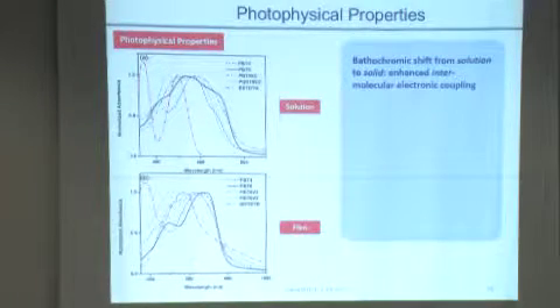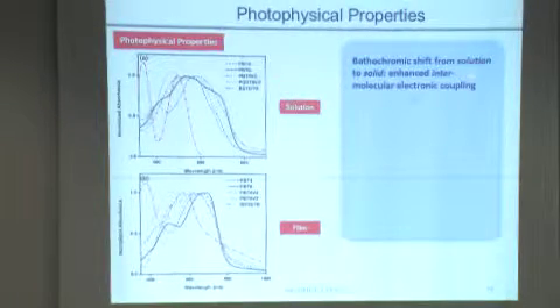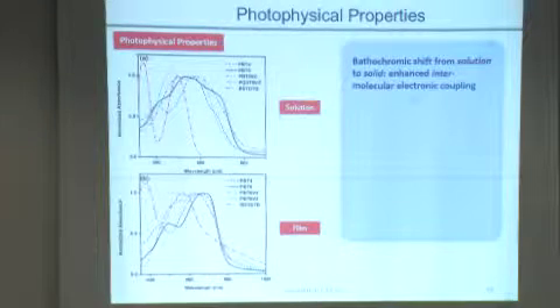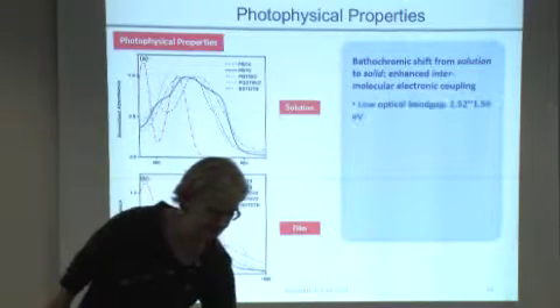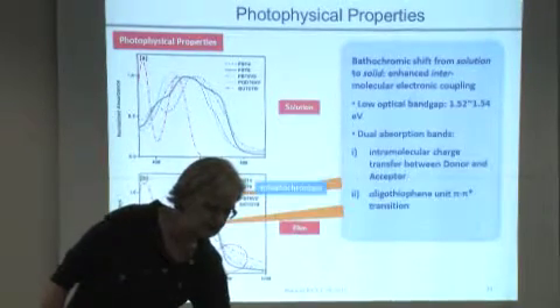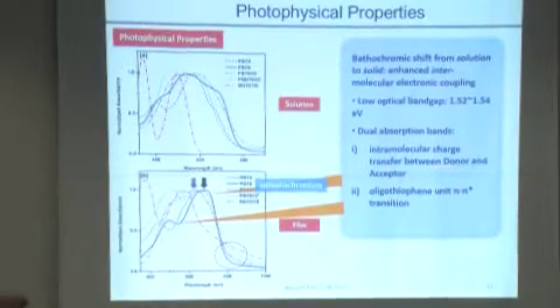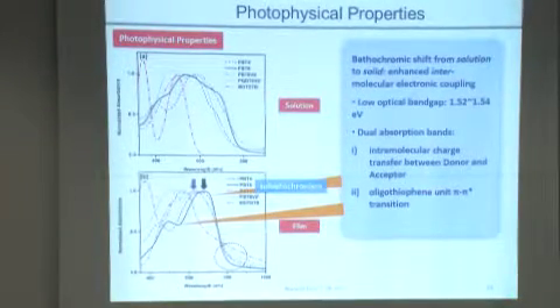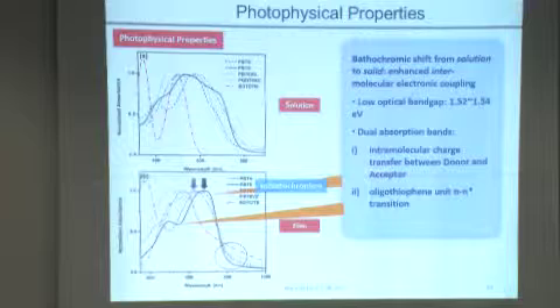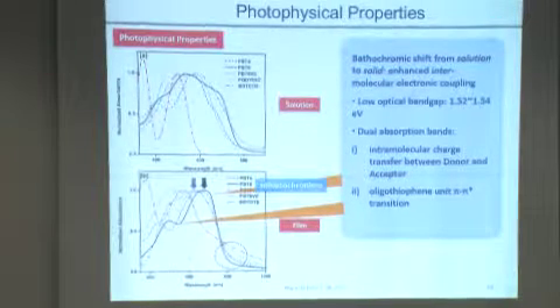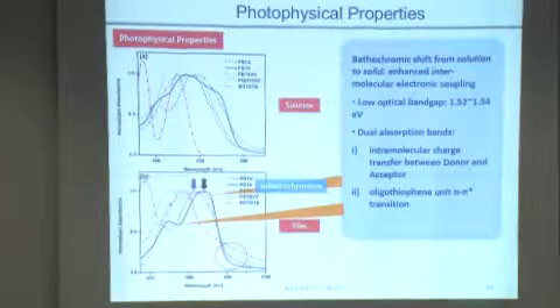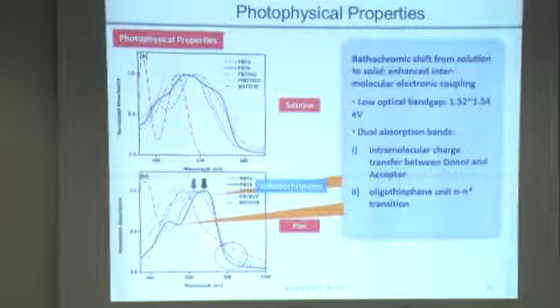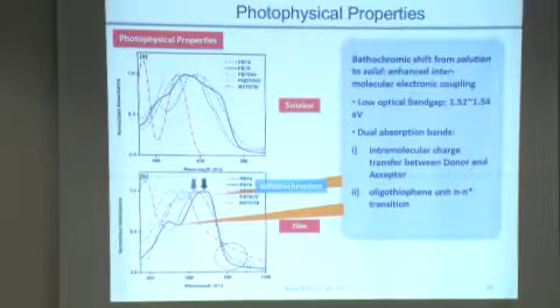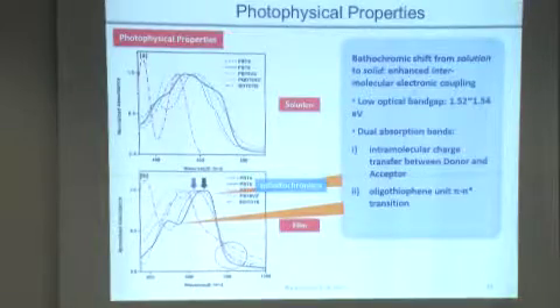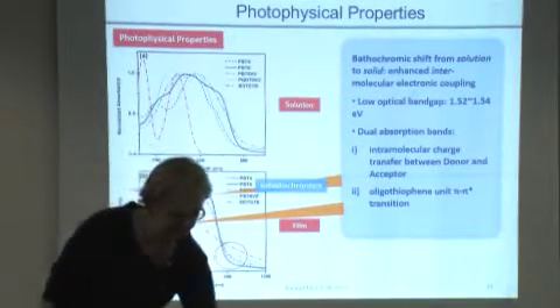If we look at characterization, certainly there's a bathochromic shift if we go from the solution to the solid state. The material has a low optical band gap. We see dual absorption bands, one of which is an intramolecular charge transfer band between the donor and acceptor, and the other one is an oligothiophene transition for the pi-pi star transition.